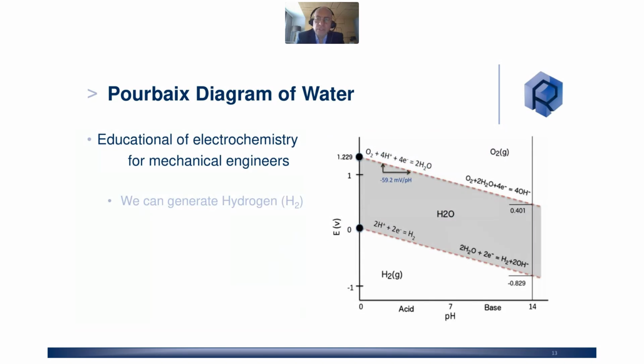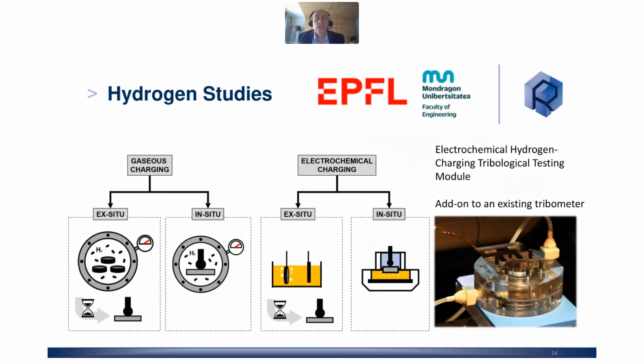For those of you that are not familiar with electrochemistry, the idea is relatively simple: if you apply a potential in a liquid environment, you are able to generate hydrogen. This simple idea in electrochemistry was taken as an advantage in the setup at EPFL, in order to generate hydrogen simply by applying a potential in a specific liquid solution and simulate hydrogen embrittlement in steel material, as an example. Of course, there are many technical details on this hydrogen testing, but it is in reality a relatively easy add-on to an existing linear tribometer in order to do studies under a hydrogen environment.